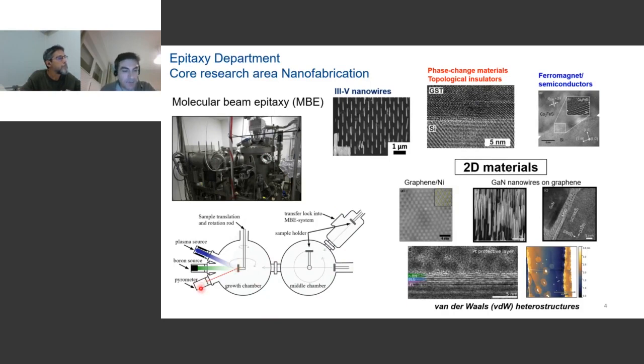You then have the different ports, as I mentioned, where you have the material that you want to deposit. In the case of boron nitride, we use a boron source that is loaded with elemental boron, highly pure boron. We heat up this material to high temperatures, and then you get sublimation.